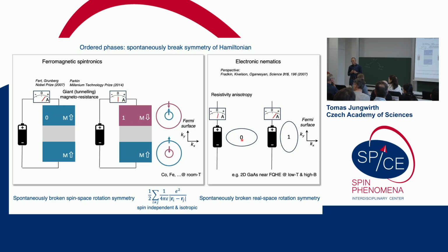Bilayer strontium ruthenate 327, there is a range of magnetic fields between 7 and 8 tesla. You think that works. There is the nematic phase, which is actually observed in the transport. And then in addition to that, there are all these iron superconducting materials, like iron selenide. There's a huge phase, which is nematic. Yes. So in the strontium ruthenate, I don't know if the situation is already clear, because I was at a meeting where there was still a heated discussion whether it's really a true nematic phase or whether this is some structural thing that is happening. So we need to distinguish the symmetries of the phase from the microscopic mechanism.